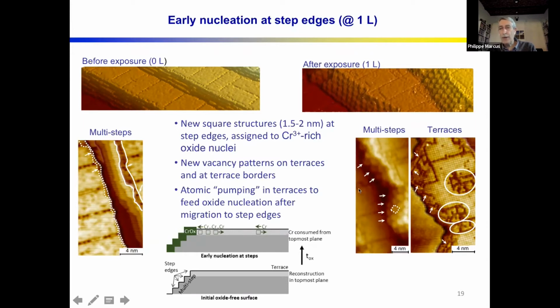This is also confirmed by the fact that we find a new distribution of vacancies. These are the vacancies on terraces after short oxidation, and the distribution of vacancies has been changed due to the role of vacancies in the transport of chromium to the step edges. We believe that this is a major observation because we can predict that there will be an area near the step edge where chromium concentration will be lower. So what will happen there?